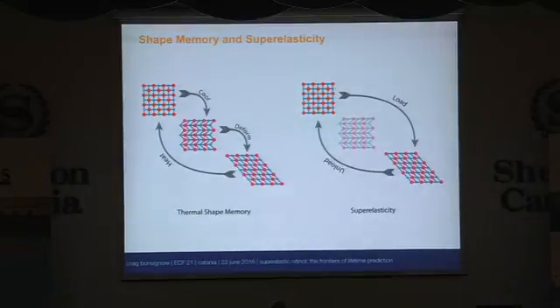So we talk about thermal shape memory and superelasticity. These are both basically, from a thermodynamics point of view, the same thing. In the case of shape memory, we are transforming phases by a temperature change. So if you take austenite and you cool it, you get what we refer to as twin martensite. So those atoms kind of twist and fold into this kind of accordion shape without changing the bulk shape of the structure. And then once that transition has been made, the structure can be deformed very easily with very little stress.